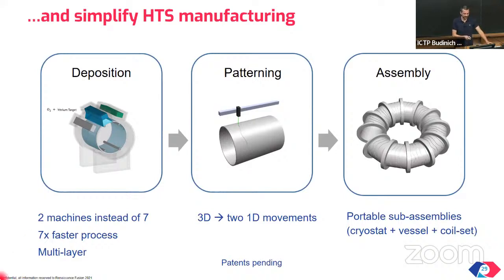The result of this deposition process is a cylinder that superconducts in any direction, which is not what we want in reality. What we want is specific current patterns that generate the specific magnetic field geometry needed for Stellarator confinement. So what we do is with a laser, we ablate this cylinder in specific locations. Effectively, we make grooves in the cylinder.